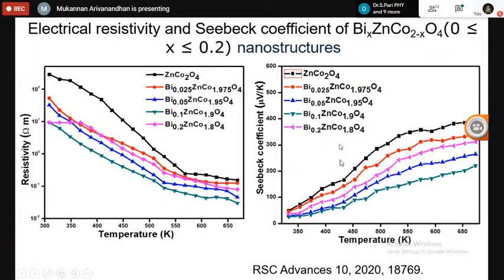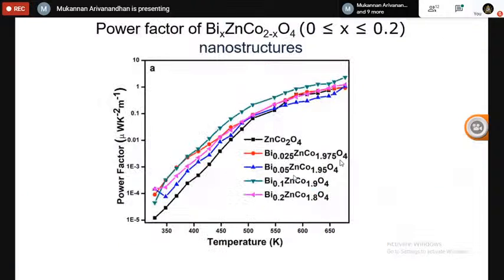Okay, and the Seebeck coefficient also systematically varied with respect to the bismuth content, and that shows the relation between the electrical resistivity and Seebeck coefficient in the system. And from the measured electrical resistivity and Seebeck coefficient, the power factor has been calculated, and the power factor is quite high for the bismuth substituted sample compared to the bismuth free sample.